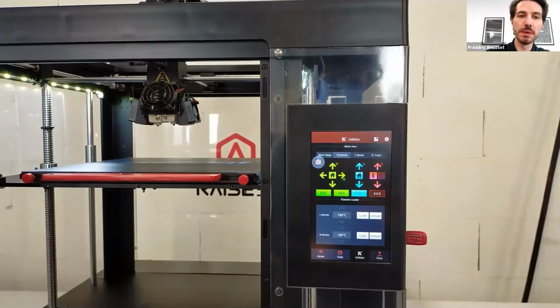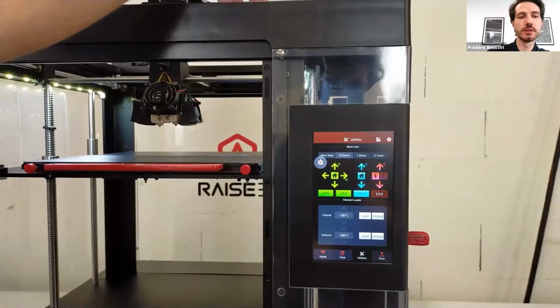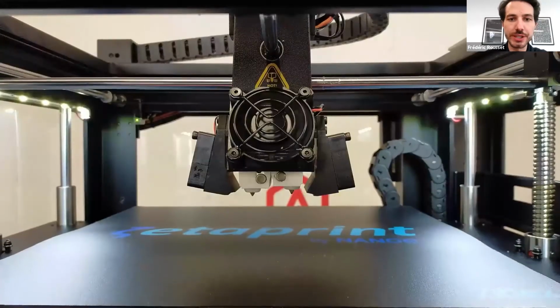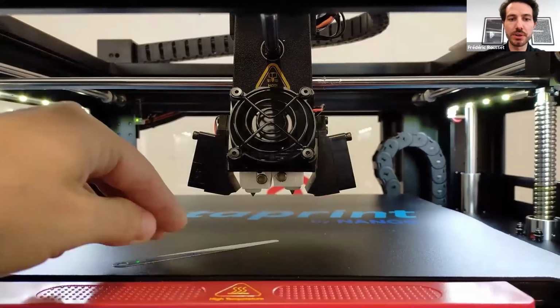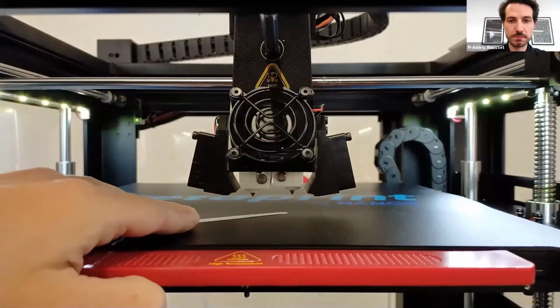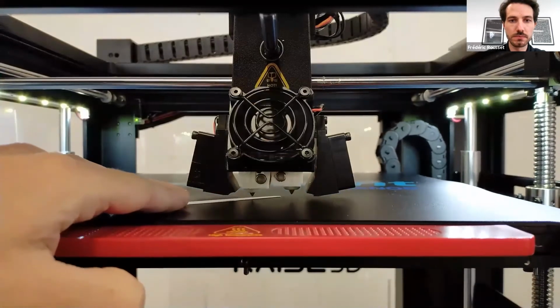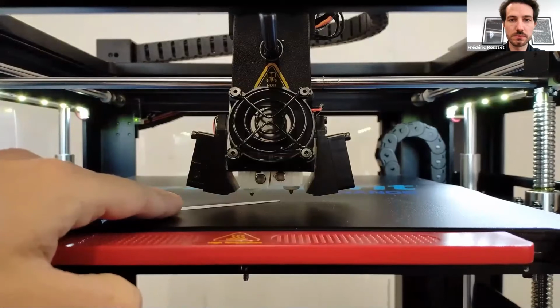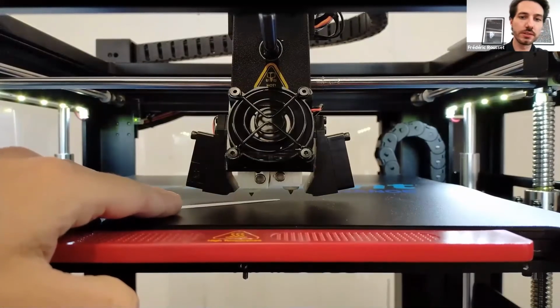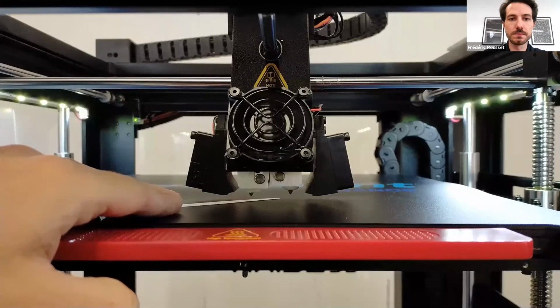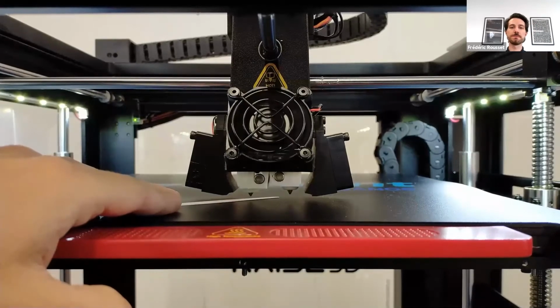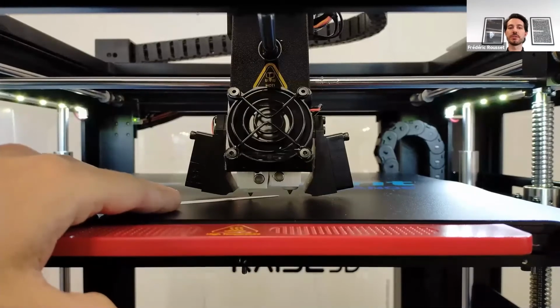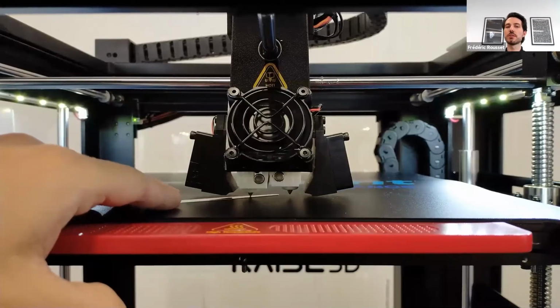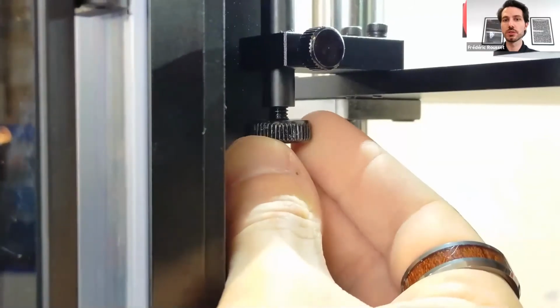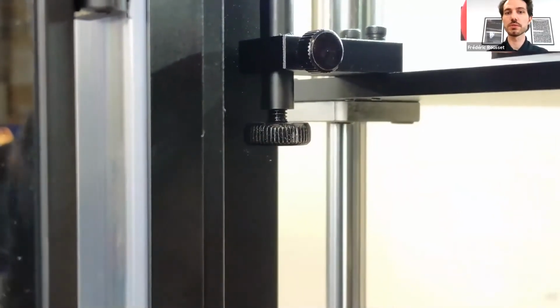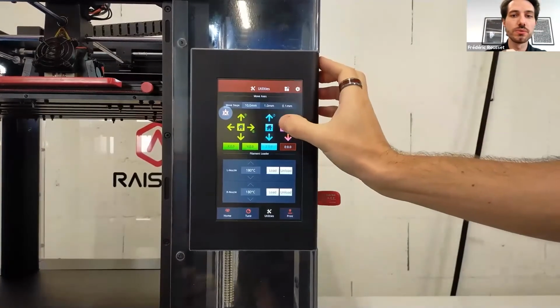So I'm doing the bed leveling. This is very important so that the first layer is well deposited on the bed. I'm using a metallic part just to set the bed leveling. This is a really important part. It can be quite sensitive depending on the filaments that we are using. You have to get a bit of a hand for it. This is the only part where you need a couple of hours or minutes to get the hang of it.